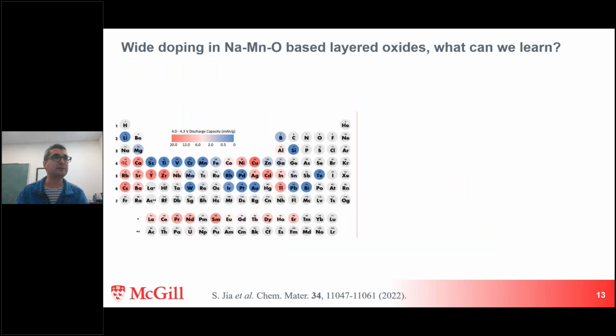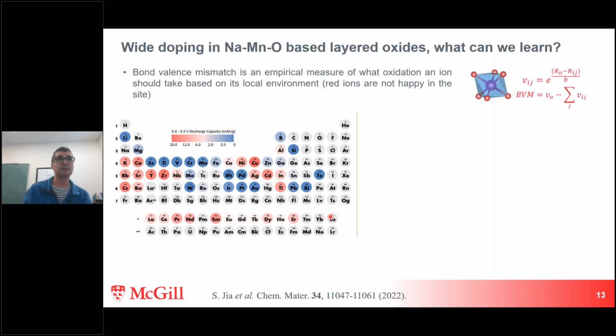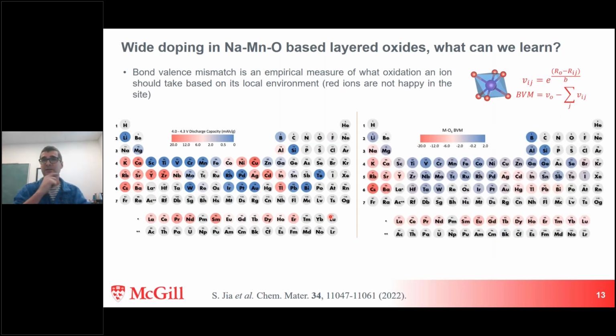But we found a metric that was able to predict what induces this anionic redox. So first of all, which elements do cause this redox? If we look at the 4 to 4.3 volts, so the high voltage, then in red, we get three regions in the periodic table. We get a region over here, and then over here, and in the lanthanides. We tried a number of different things, and then we found that something called the bond valence mismatch does a really good job of predicting this. We find all three hotspots are lit up by this bond valence mismatch.